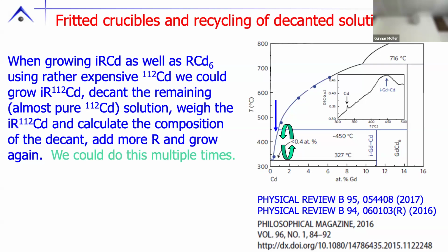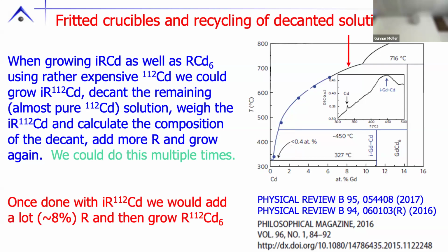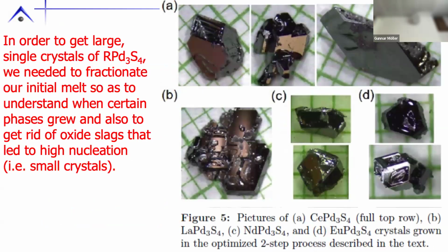So what we can do is we can do this multiple times. We figure out how much of this we grew. We know the composition of the decant, so we can add it in again and again and again. And when we're all done, we can compare to the crystalline approximant, put in a lot more gadolinium and grow it out. That way we're not wasting very expensive material. We do the same thing with platinum and palladium growths, although they are cheap compared to this. Now, the word fractionate is generally associated with the petroleum industry, where they're evaporating off different fractions of hydrocarbons.